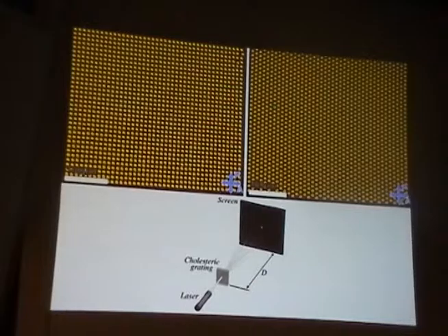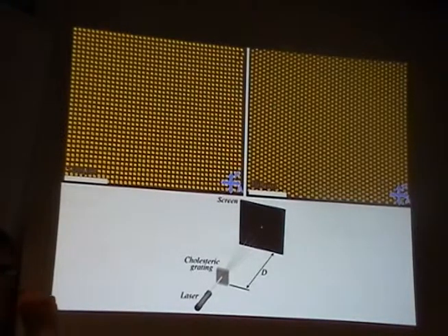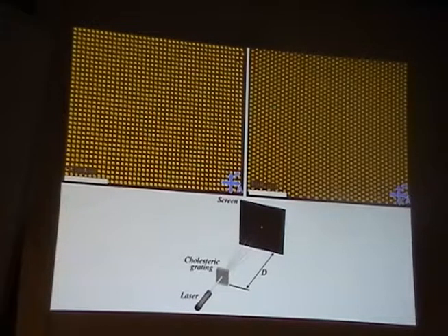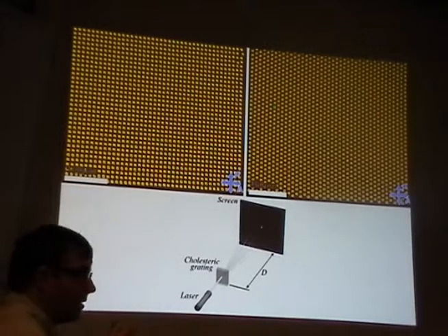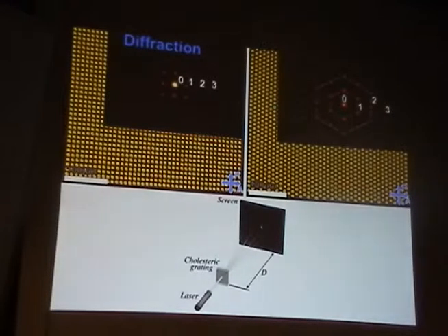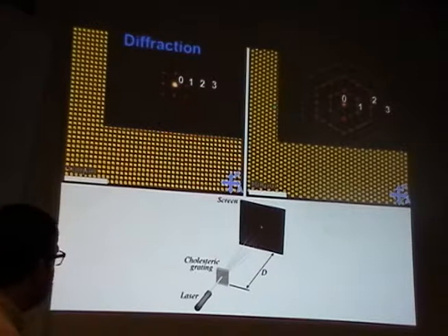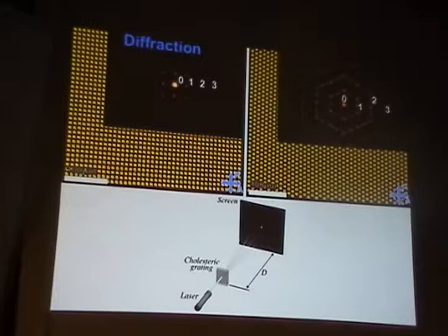Here we have square periodic and hexagonal lattices, and in this case, to generate them, we use somewhat higher laser power, so that the location of the torons is pinned exactly in places where we focus the laser beam. Obviously, if you now use such a periodic array as a diffraction grating, you could obtain far-field diffraction patterns such as the ones you see here on the slide.